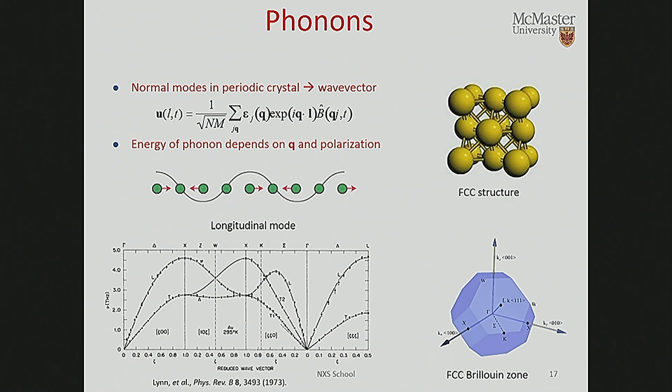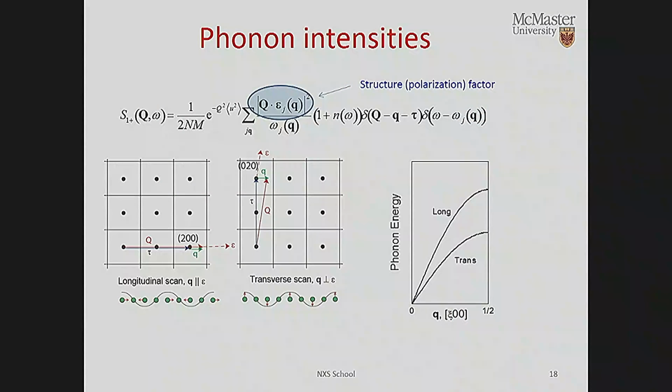Yeah, that's right. If you imagine that the atoms were all connected with springs, here you're really directly compressing the springs. You're moving the atoms directly towards each other, so you're maximally compressing the springs and then maximally extending them. Whereas if you move them like this, you're kind of shearing the springs. So this is almost always a lower energy mode, and that's why this is a lower energy phonon than these are. But you can see anyway that it's relatively straightforward to map out all these phonons, and that's been done.